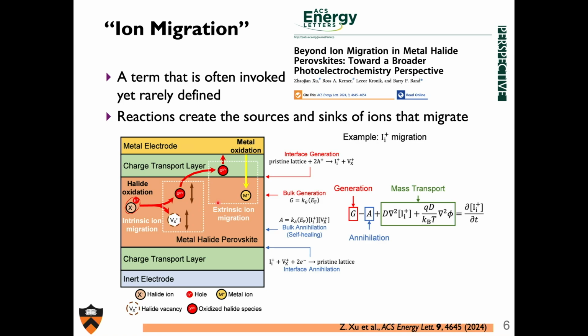And in order to make progress here, here's an example for the one that keeps me up at night, which is interstitial iodide. And so you have maybe a place here where you can generate interstitial iodide and halide vacancies. You could also have bulk generation. You have bulk annihilation. That's basically what's known as self-healing. Basically, these reactants, or in this case, the products of this reaction, are newly formed reactants to reform the perovskite lattice. And I can have annihilation of these vacancies and interstitials to join the lattice again. And that's all mediated by things like generation, annihilation, and mass transport, either drift or diffusion, of these interstitial ions.